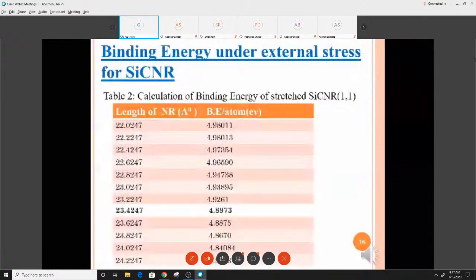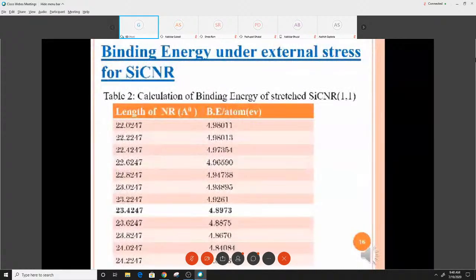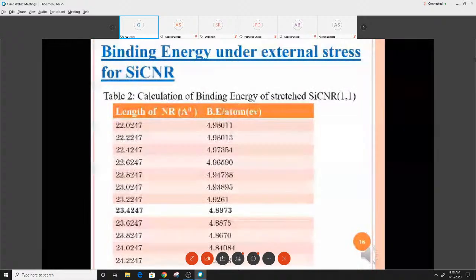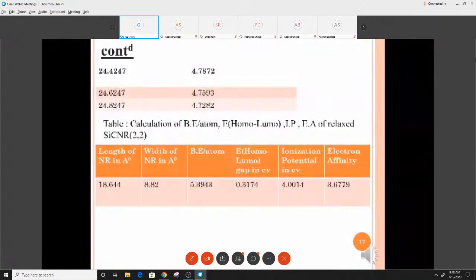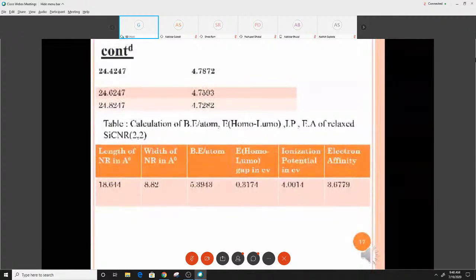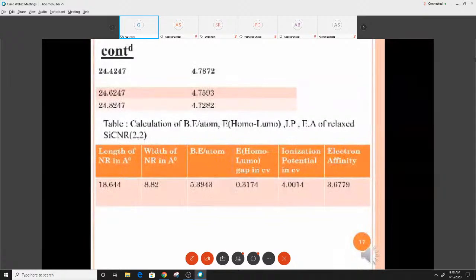It gives the binding energy under external stress, length versus binding energy per atom. It shows that binding energy per atom decreases when we increase the length of the nanoribbon. This is the continuous data, and the second table is the 2 armchair silicon carbide nanoribbon. It is just the optimized structure, and binding energy per atom increases here.